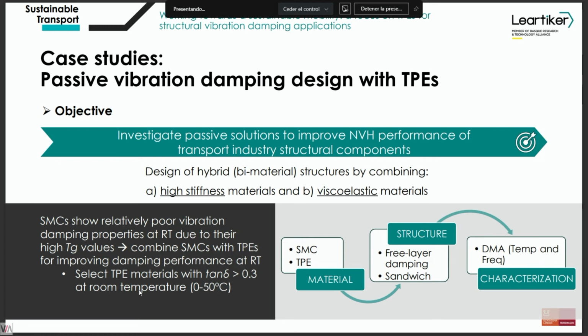As I will explain later, we use loss factor, which is a property that can be captured by DMA, because this factor is related with the dissipation ability, or the intrinsic dissipation ability, of materials and gives information of this structural damping capability of materials. Okay, so as I said, we have selected several materials with these specific properties. We developed some structures. We developed during the project two kinds, free layer damping and sandwich.